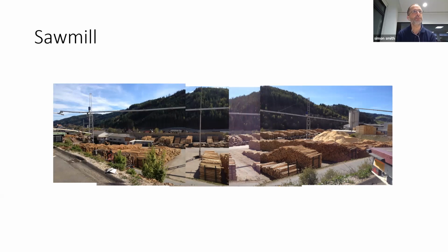And you can see here a sawmilling factory with the wood literally taken down from the hills by the side, and then the logs coming in and getting sawn, the waste from those, and that processing of the logs, firing a biomass boiler, so heat and power generated, and then those logs getting changed into sawn wood, kiln dried with the heat from the biomass, and then made into either glulam or CLT, in a factory process. The rate at which material is processed is quite phenomenal.